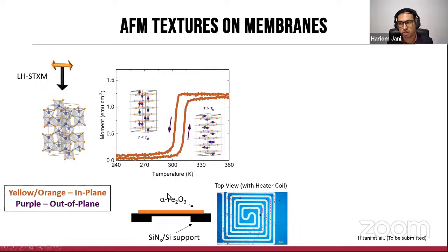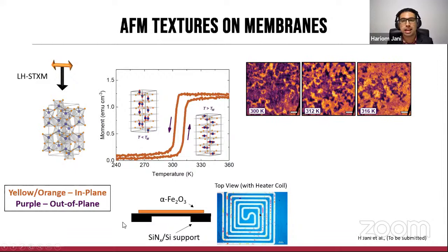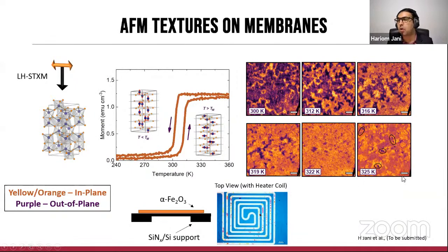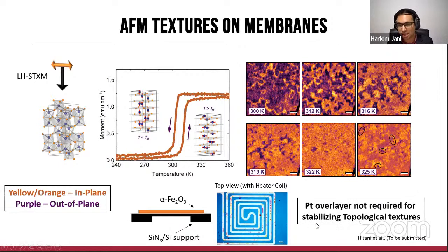Now, this system also hosts a Morin transition when doped appropriately, and this is close to room temperature. This was carefully crafted because we wanted to meet the system requirements at the STXM. And again, what we observe is that as we drive the system from the low temperature domain wall state to the high temperature, we actually retrieve all the topological objects in the system just as before. Now, an interesting feature to note here is that this sample does not have any overlayer. There's no platinum here, and still we are able to observe these textures, which convinces us very strongly that platinum is actually not necessary to stabilize any of these objects.